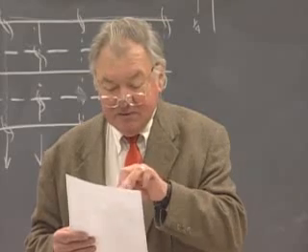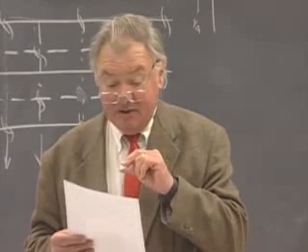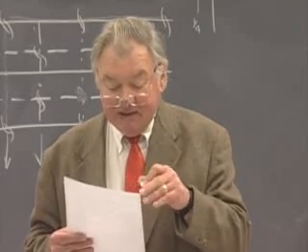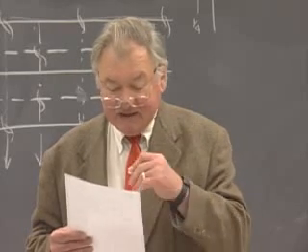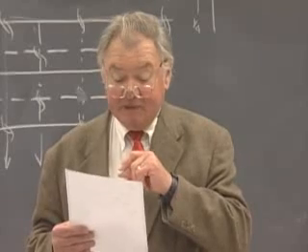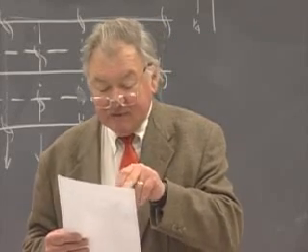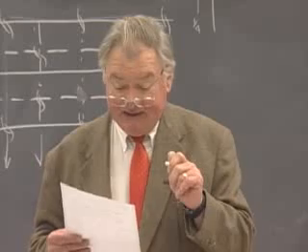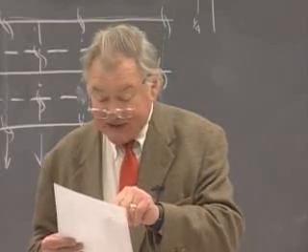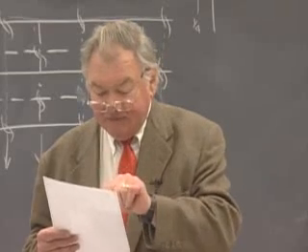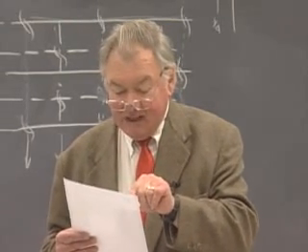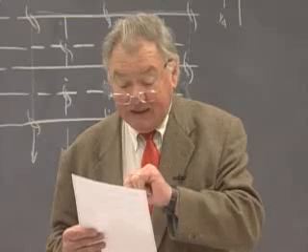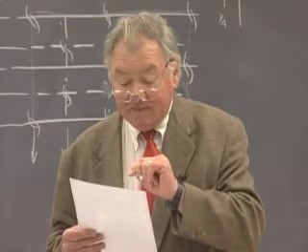Alongside of each circle, you will see two symbols giving the elevation of that atom within the cell. The one at the furthest upper left corner says 1/2 plus, so this says that the coordinate is z, whatever that is for the representative atom, plus 1/2. The half of the circle that has the comma inside has a minus sign next to it. That means that it is at an elevation minus z. Well, where is the representative atom? This is tucked just inside the corner of the cell where the vertical line divides the circle into 1/2. That is a plus, so that's an atom at plus z. The right-hand side of that circle has a comma. It's an enantiomorphic motif, and that exists at 1/2 minus z.